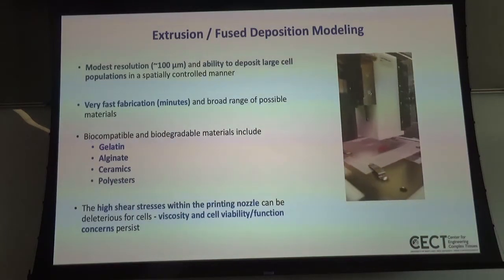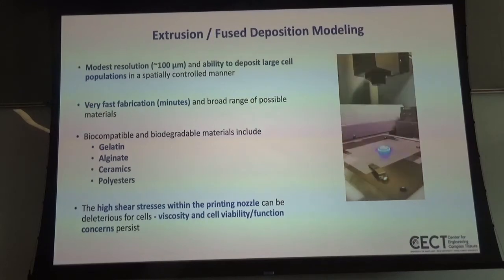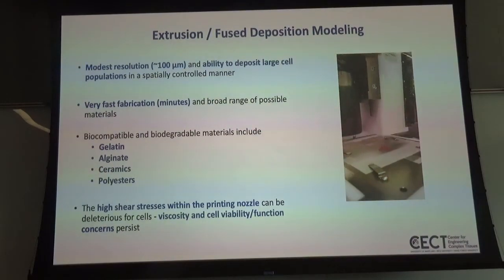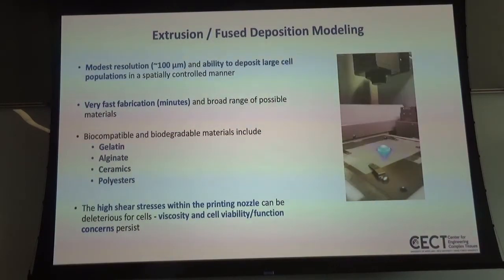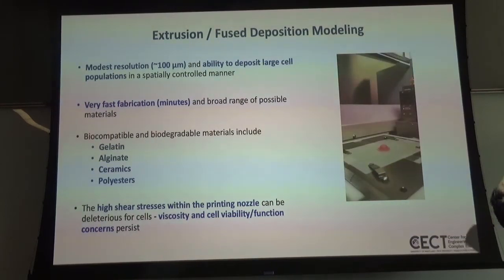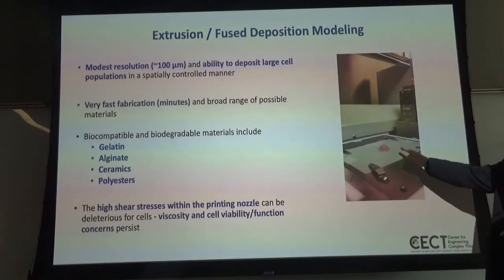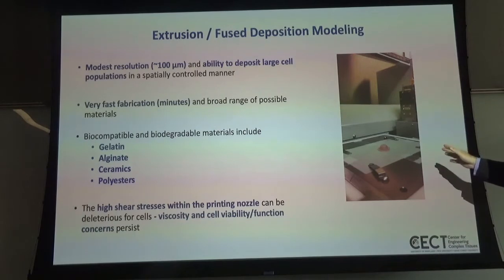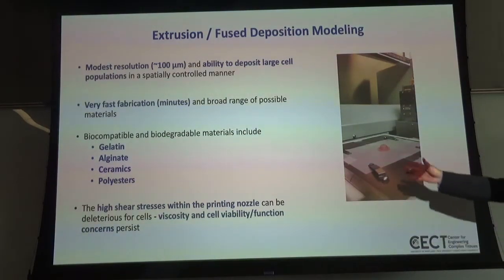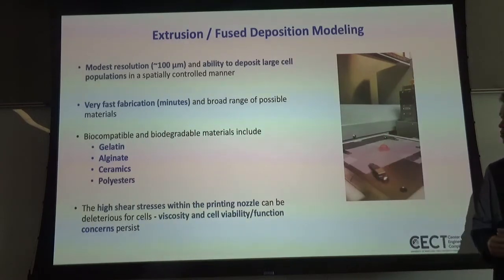The extrusion-based printing approach is very nice because it really allows for cell-based printing. The resolution, since you are extruding fibers, is a little bit less, probably starts at about 100 microns and goes up from there. But you can incorporate a viable, functional, healthy cell population. The fabrication is fast. It's not that fast, it's on the order of maybe 10 minutes, not 10 seconds. And again, you have a variety of materials that you can choose from.